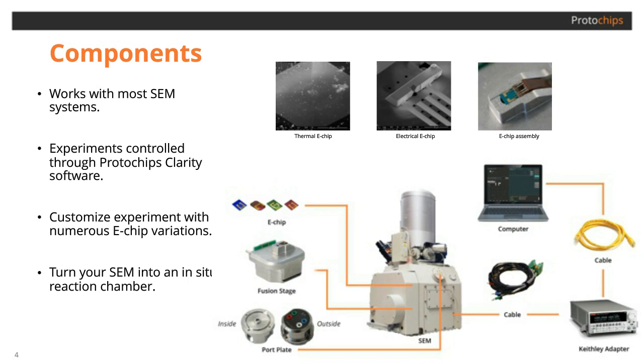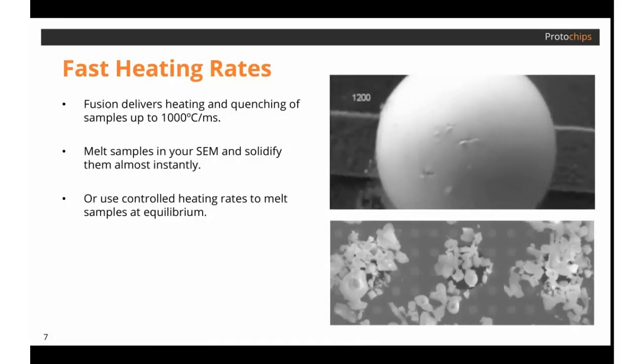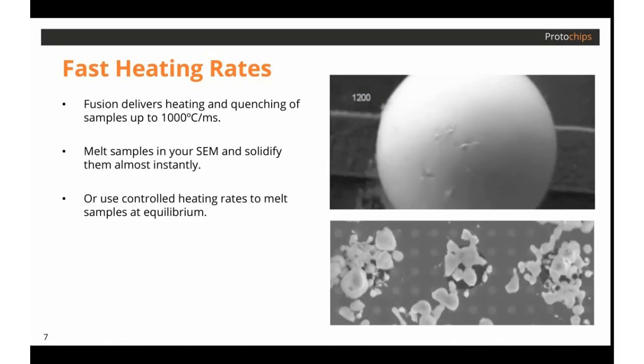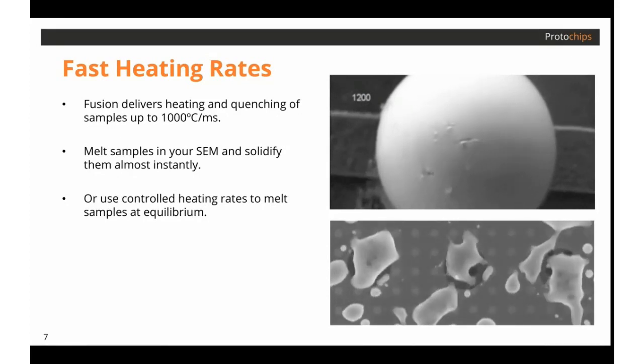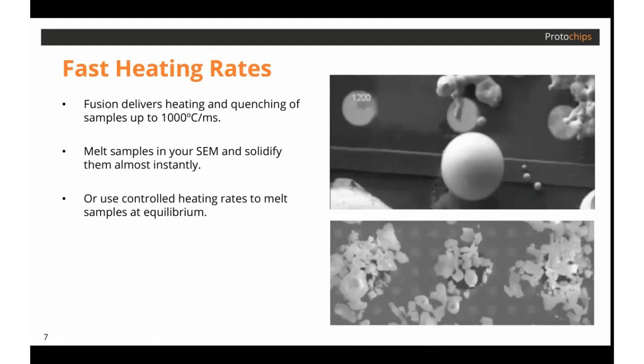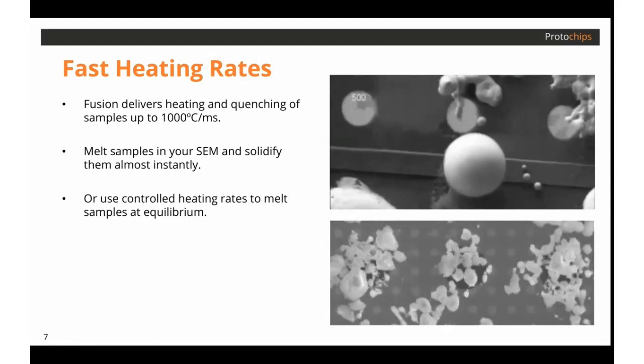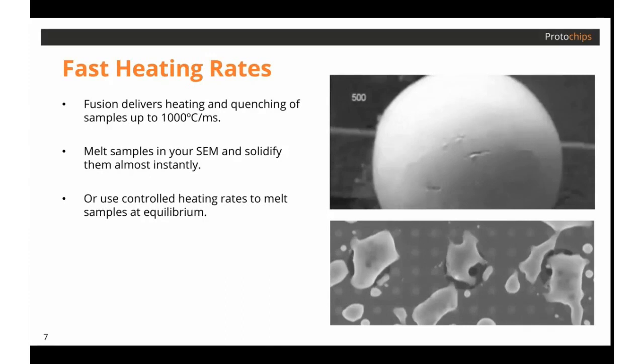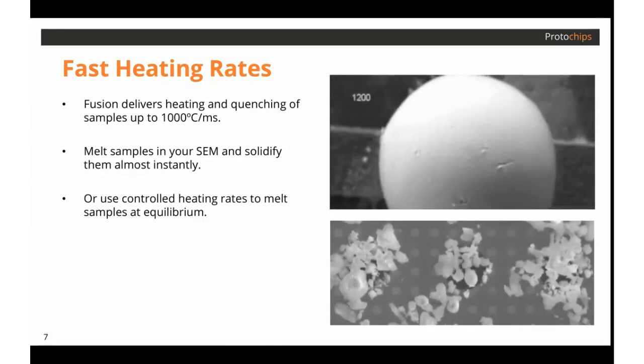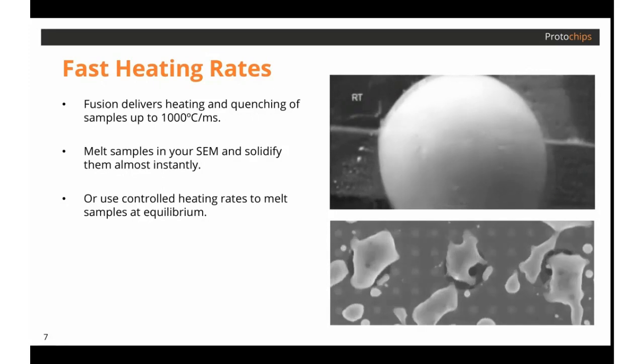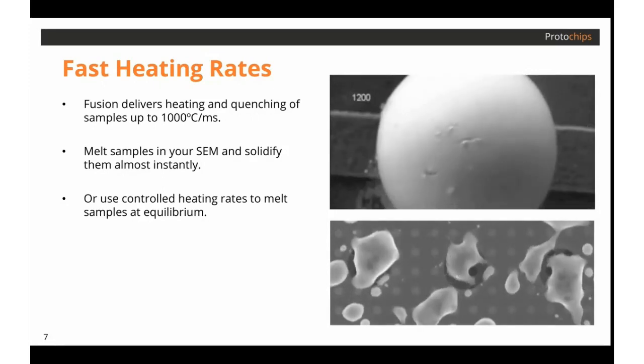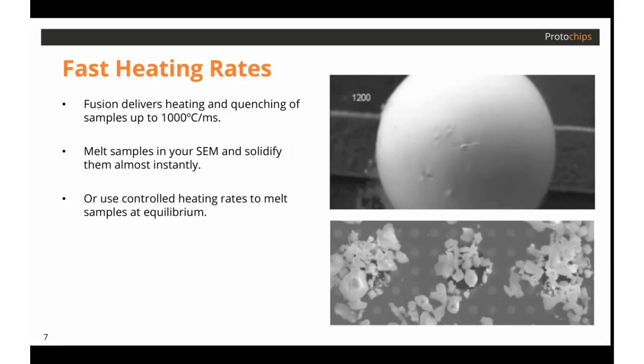So for one, Fusion heats and cools really fast. It can reach temperatures up to 1200 degrees C in just over 1 millisecond. So this is perfect for studying ultra-fast phase transformations like martensitic phase transformations, but you can also do liquid melting and solidifying all within the microscope. So here you can see a copper-silver particle, which is solidified from its molten state almost instantaneously.